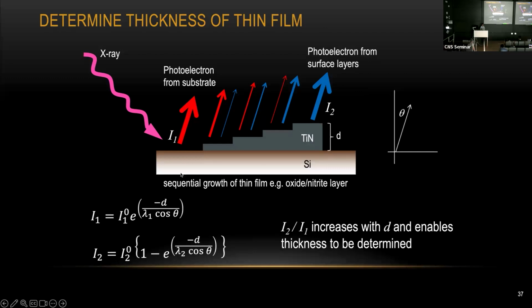So the cartoon here is just a very simple substrate, the silicon substrate. On top, we coat it with some titanium nitride film. So when you do the measurement on your substrate here, all the signal coming out from your sample is just a silicon signal. And if you go to some very thick region, anything beyond 10 nanometer, everything you're detecting here is simply titanium and nitrogen. But in between, you can see a mixture of different signals, silicon, titanium, and nitrogen with different intensity. So by plugging in all the intensity information here, we actually can determine how thick you have for each layer.